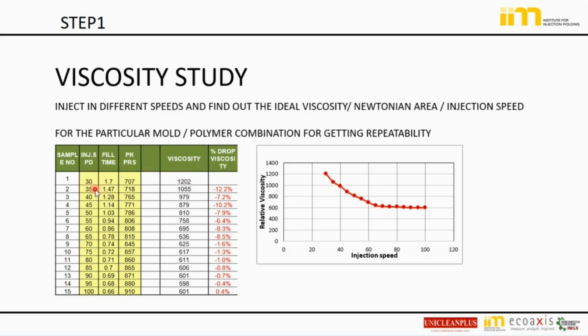Then after 30, we make it 35, increase the speed, and again we put in the filling time and peak pressure, whatever we are getting. Then after 35, go for 40, in increments of 5: 40, 45, 50. Against each injection speed, whatever actual filling time and actual peak pressure I get, I put across, and the viscosity is calculated. Beautiful chart, no? You can see it on the right side: viscosity with respect to injection speed. With different injection speeds, you can see the viscosity keeps changing.